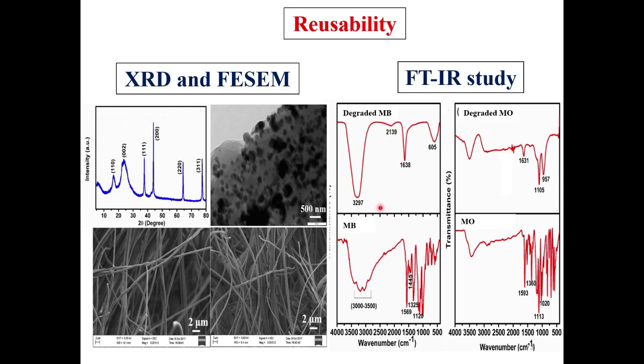The change in the nature of the peaks suggests that methylene blue is degraded. For methyl orange, before degradation and after degradation, it has been observed that the additional peak from the pure methyl orange is removed in the degraded methyl orange, suggesting that the material is getting degraded, and the effective degradation happens with the help of the PAN silver graphene sheet nanofibers.